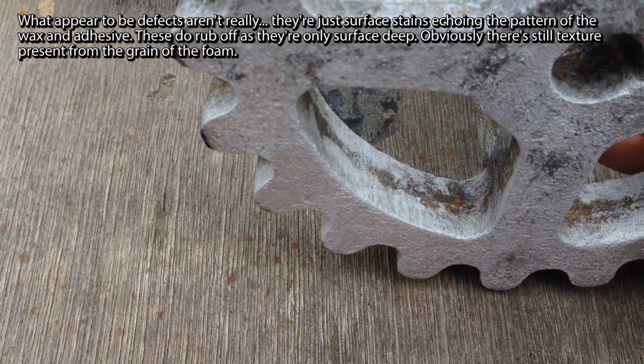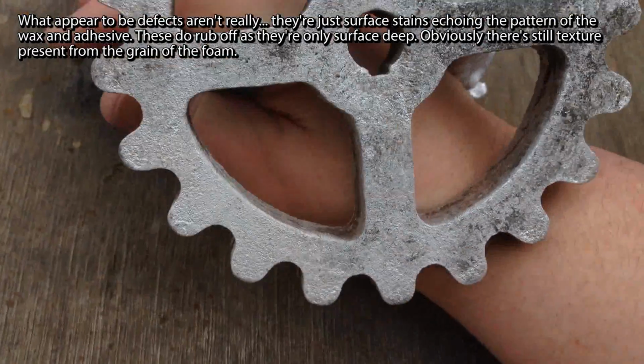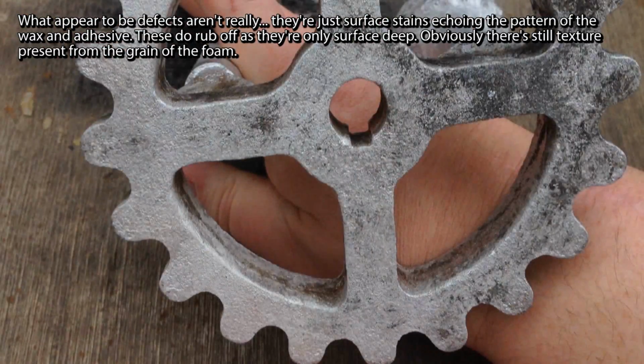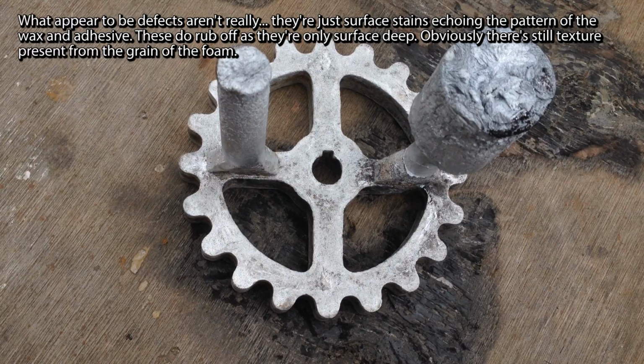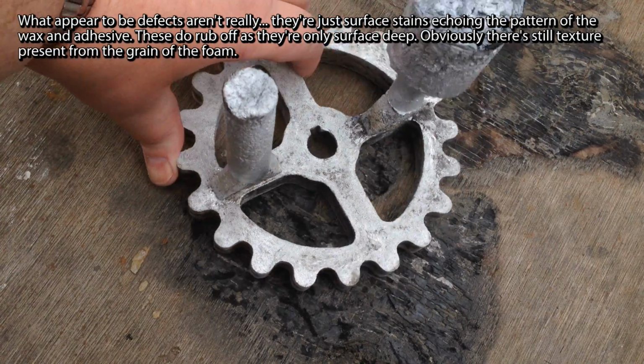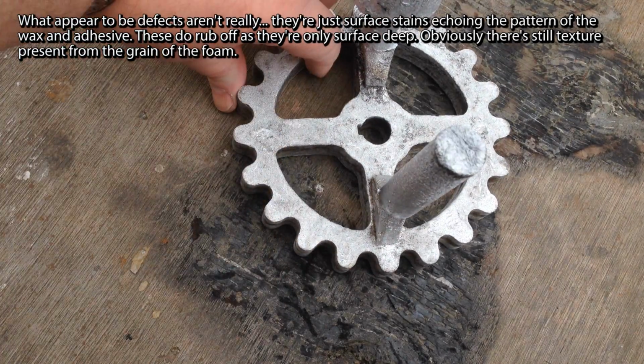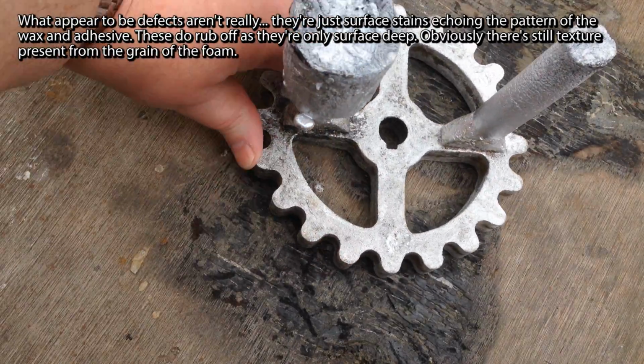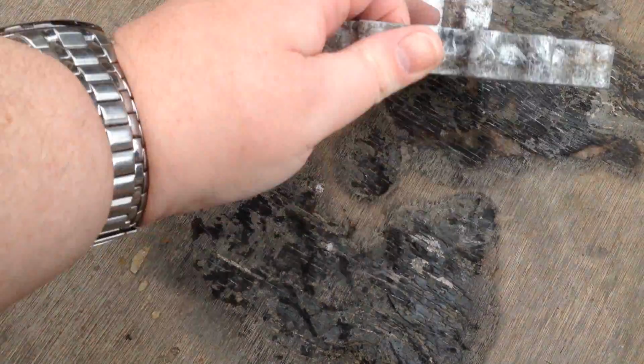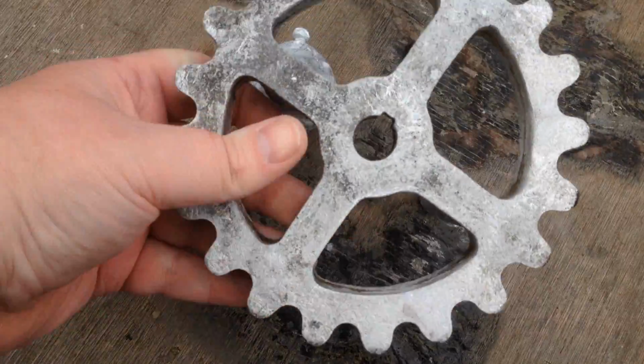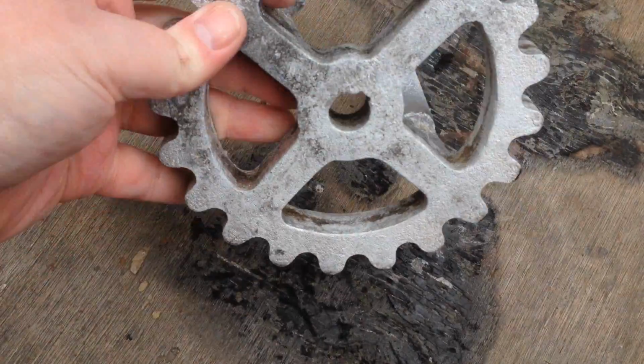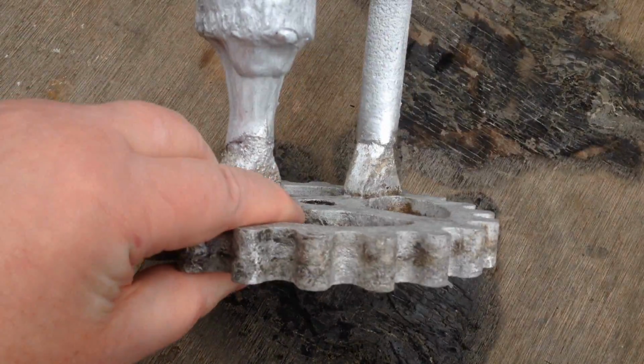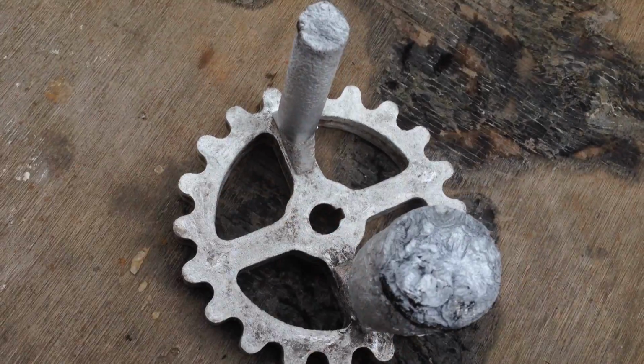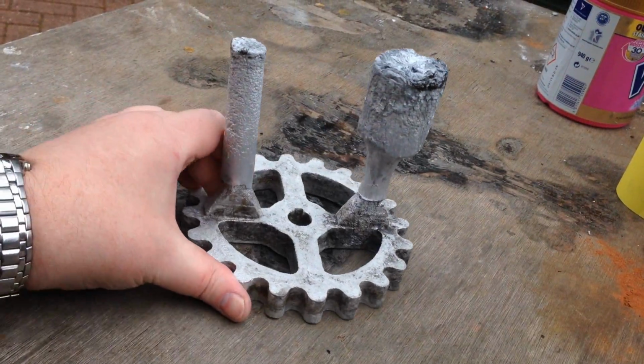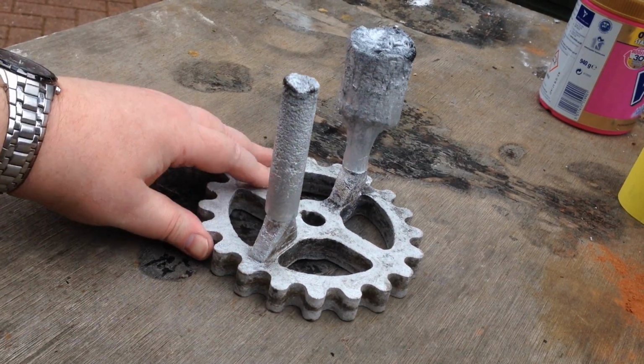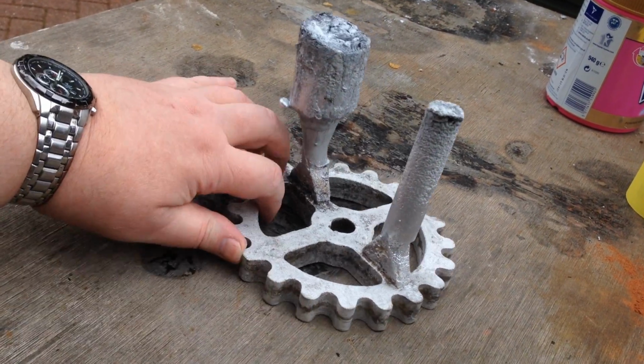I suspect that these are only surface stains, some sort of thin deposit of decomposition products from either the foam or the wax or the adhesive. A quick rub with sandpaper or a file removes these, but I wanted to show you it in its raw state. In truth, I can't do this sprocket justice with a camera. The texture of the foam is evident, and the metal in the areas that were filled with wax are smoother by comparison. It really is a nice job.